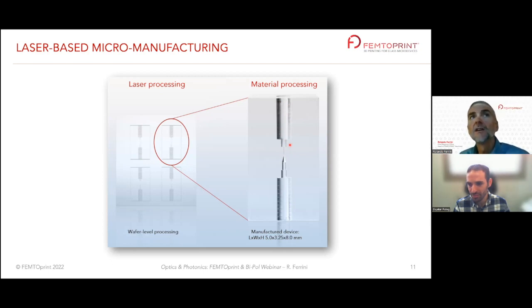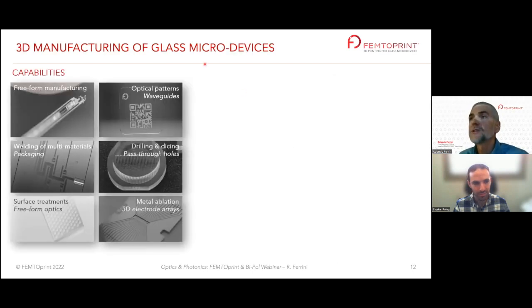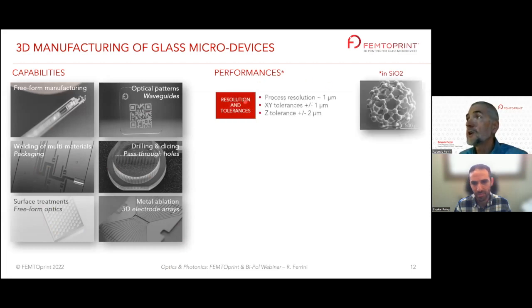So we have now more than 10 years of experience on the process. And this allows us to do all the things I've told you before. We can 3D manufacture glass with free-form capability and monolithically integrate several functions in one single device. We can write things into the bulk of the glass. That's important for photonics. Come back to this later on. We can weld glass to glass, but also glass to silicon carbide. It's important and interesting for packaging and assembly. We can drill holes and vias. We can generate microstructured surfaces, and we can ablate metals.